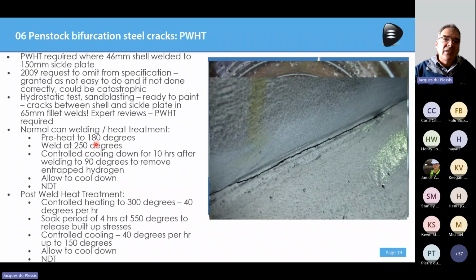So you preheat the steel to 180 degrees, then you weld at 250 degrees. This is the normal welding and heat treatment. And then there was a controlled cooling down period for 10 hours to 90 degrees, just to make sure that all the entrapped hydrogen was removed from the weld. And then you allow it to cool down by itself, and then you do your non-destructive testing.